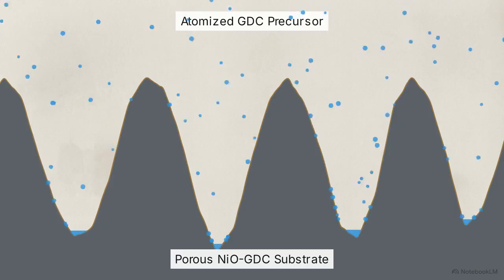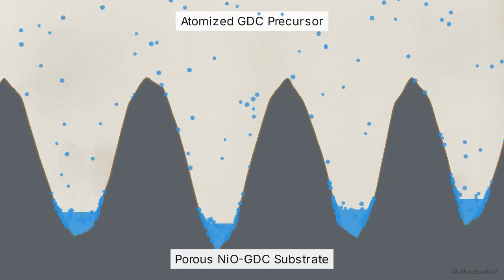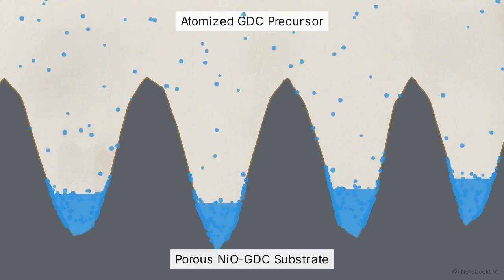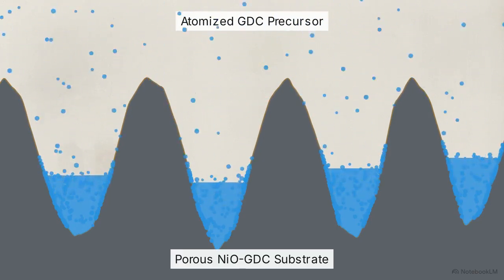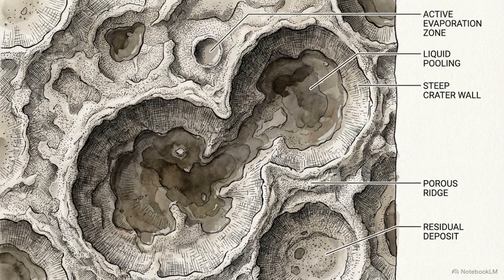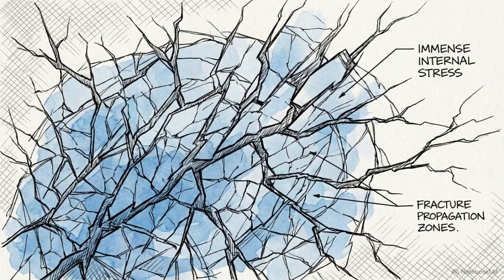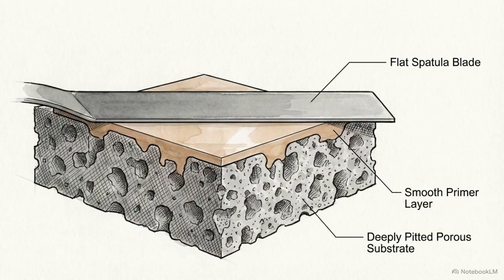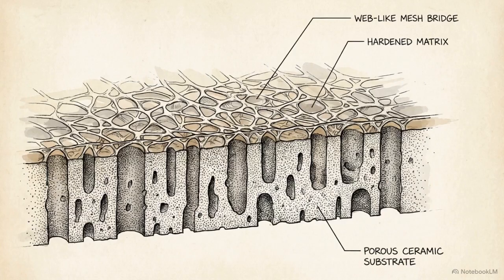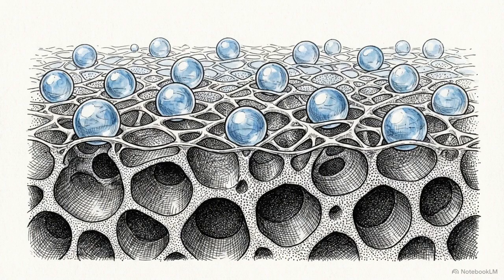On a porous surface, the droplets cannot easily form a continuous bridge. Instead of layering on top, the atomized precursor soaks directly down into the microscopic pores. Furthermore, the uneven texture of the ceramic causes the solvent to evaporate at different rates across the surface. This uneven drying creates immense internal stress, resulting in massive microcracks across the forming film. To prevent this, Dr. Chourashiya applied a surface modification to the anode-grade ceramic prior to spraying. By treating the top layer of the porous sponge, he altered its physical structure just enough to catch the decomposing droplets without letting them soak through. The integrity of the final thin film relied entirely on preparing the substrate below it.